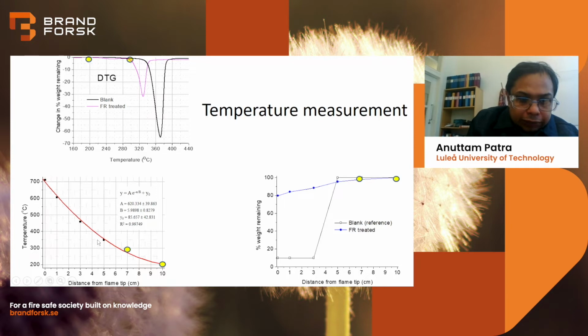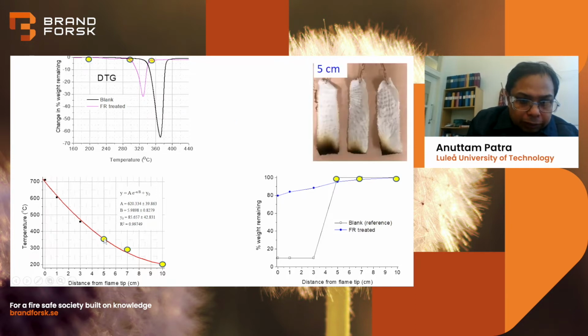When the distance is even less, 5 centimeters, the temperature reaches 350 degrees, which is just above the decomposition temperature of the treated cloth. Then we see a little more change, but for the untreated pure cotton, there is no weight change.